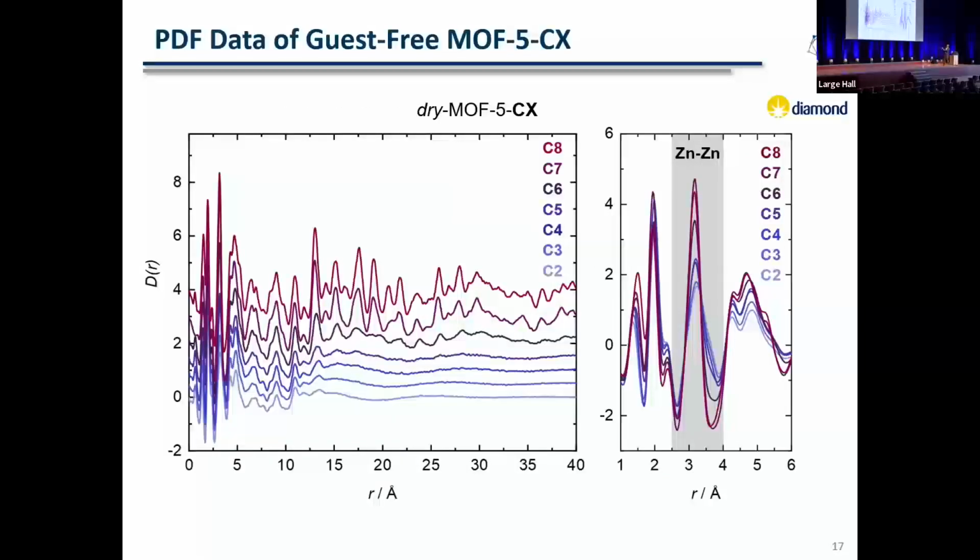Now when we compare the entire series, with the different carbon side chains, these are the rhombohedral ones, and they are crystalline. The C6 is a bit of a border case. There are some correlations here still, but then they diminish. And for the other ones, C5 to C2, they are non-crystalline and the correlations vanish at about 15 angstroms again.